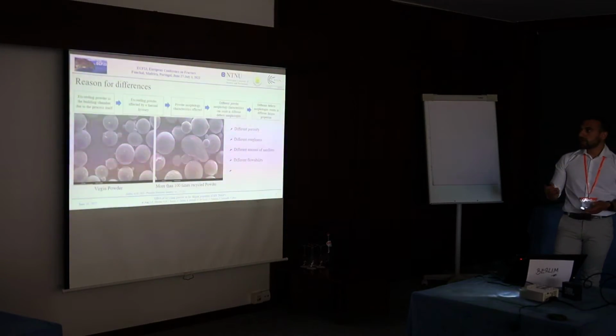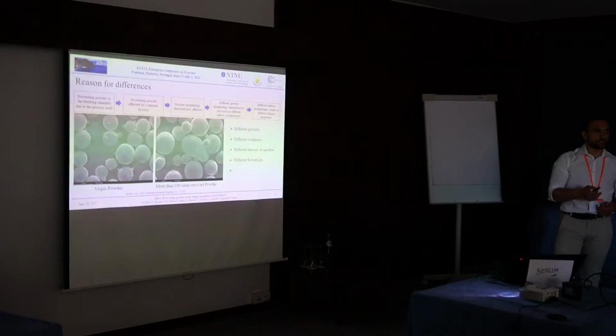In this case, the exceeding powder can be collected and used again to build other components. But of course, we have to consider that in the previous processes, the powder has been affected by thermal history in the building chamber, and this thermal history could affect the morphologies of the powder. Different powder morphologies can result in different defect morphologies, and also in a different roughness of the specimen, which can result in different fatigue properties.